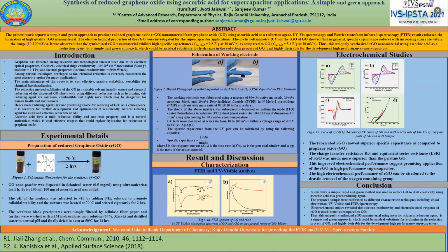Electrochemical impedance spectroscopy concluded that the charge transfer resistance of reduced graphene oxide and graphene oxide was quite different, which shows that reduced graphene oxide has superior electrochemical behavior as compared to pristine graphene oxide. Thus, we can conclude that ascorbic acid will be an ideal substitute for hydrazine in the reduction process of graphene oxide. So thank you so much. Thank you very much.